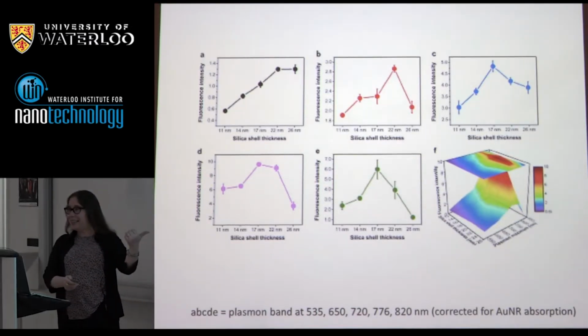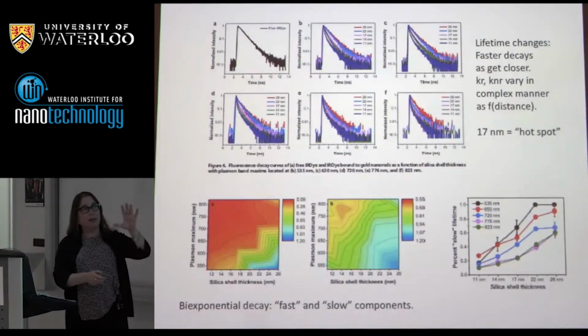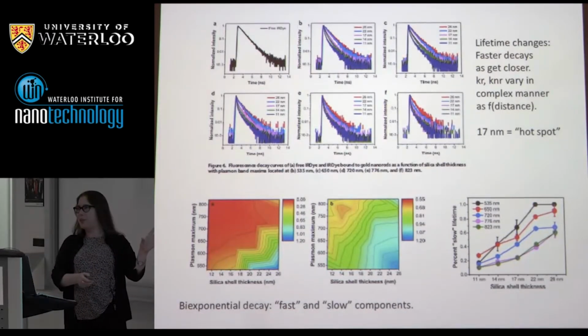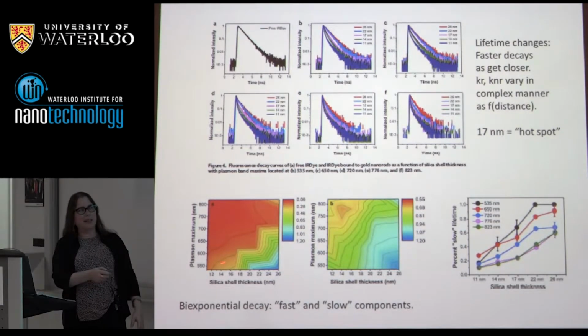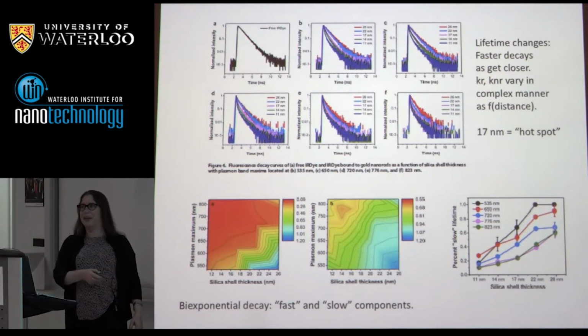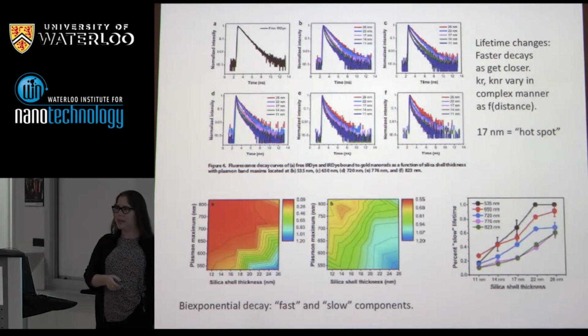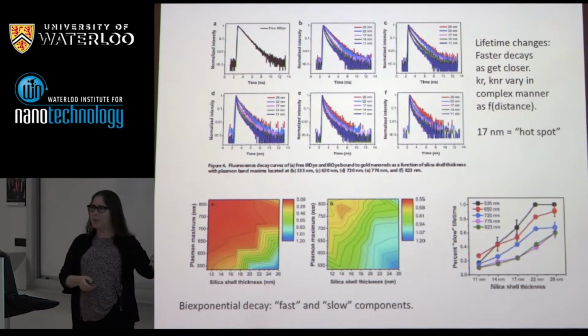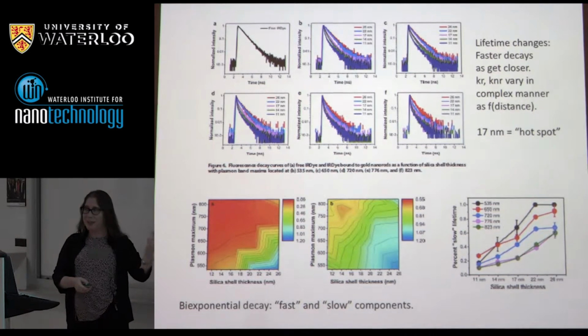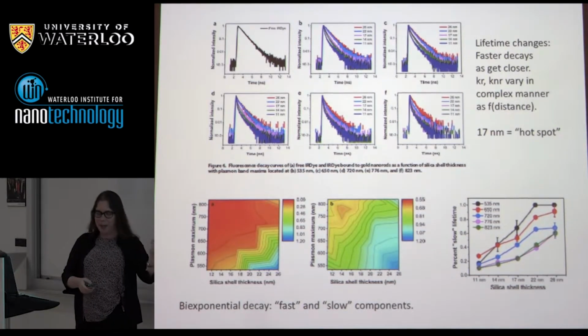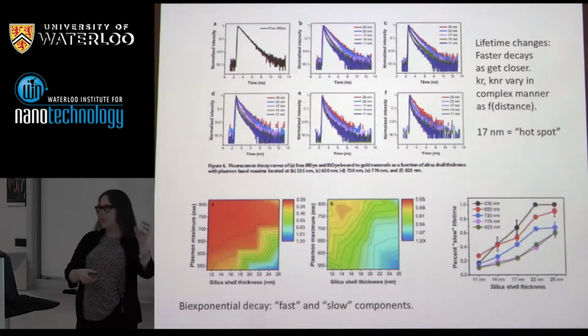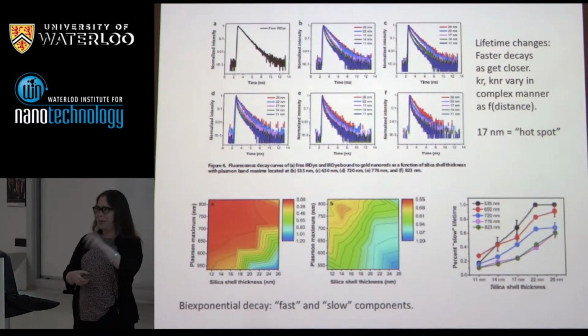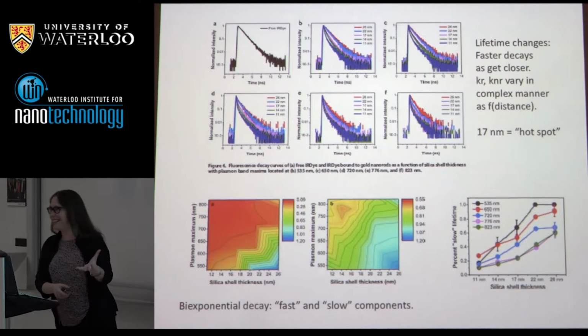When this is just steady state data here, you always want to make sure you do time resolved work to confirm your conclusions here. And this is a lot more tricky than I thought because I thought we'd be able to say a lot of words about the radiative rate and non-radiative rate of the dye pretty easily. But it turns out, right around the same time we were writing up this paper, we found a quantum mechanical calculation in the literature, and the paper was called approximately Calculation of the fluorescence quantum yield of molecules adsorbed onto gold nanorods. Okay, what are the odds?